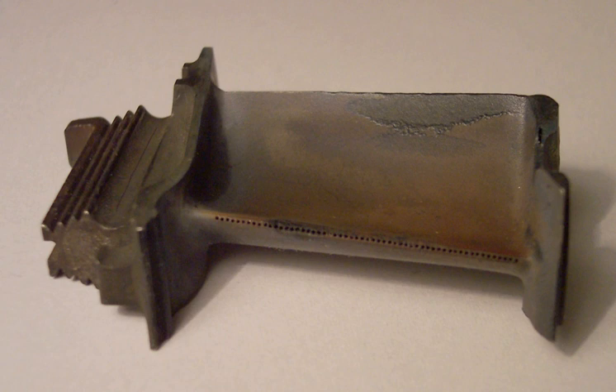The yttrium enhances the oxide adherence to the substrate, and limits the growth of grain boundaries, which can lead to flaking of the coating. Investigation indicates that addition of rhenium and tantalum increases oxidation resistance.